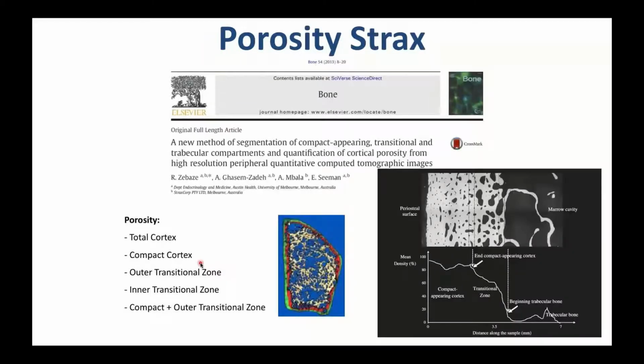So the other technique, the StrAx technique, first of all captures and identifies pores of a much smaller size, probably down to 100 microns or even less. And then it has the ability not only to measure the cortical porosity in the cortex and identified as such, but also to somehow recapitulate the porosity in the inner cortex, even when the cortex has disappeared and looks like a trabecular structure. Some of these holes will be ascribed to the previously existing cortex. And that translates into huge differences in the percentage of porosity that comes out from these two techniques.